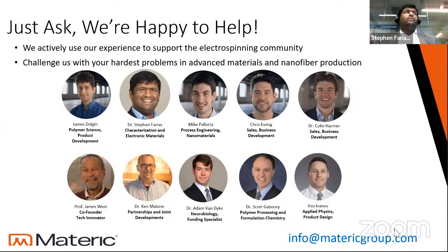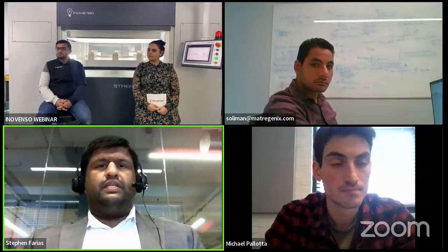Yeah, great question. So we were primarily working with some modified UiO-66 MOFs. There are a number of different MOFs available, and one of the things that's unique to them is you can tailor their chemistry. We were working with some amine-functionalized, kind of exterior functionalization of the MOFs, and that helped with the integration into the particular polymers we were working with. In terms of mixing, basically we did what Mike had shown in the presentation, where we mixed the MOFs in a solvent system using some aggressive mixing energy, so horn sonifiers, and then would go in and mix that into our prepared polymer solution.